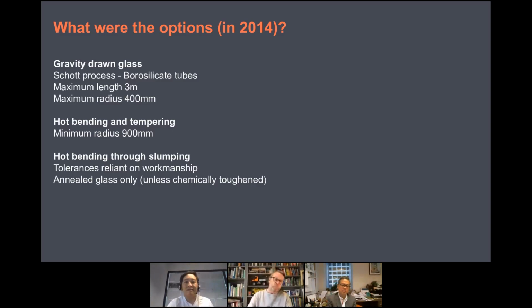Similarly, if you move to hot bending and tempering, which is more a traditional way of creating curved glass, that's been developed from the tempering process of heating it up and bending it over through a machine, which then allows the glass to be tempered at the same time. That was giving us, even today, a minimum radius of around 900 millimeters, meaning we'd need tubes of about 1.8 meters in diameter. Again, a little bit too large for what we were looking for. So forming glass and slumping was one way of looking at it, and that's ultimately what we chose to do, which involves a mold.